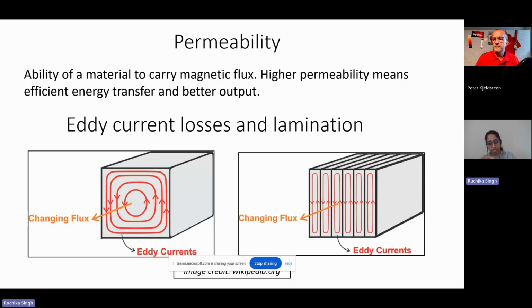coating on the electrical steel, and when you stack them together, press them and heat them up in an oven, the bonding melts, and all the stacks stick together, and there's also a layer of isolation between them. That's how you isolate the laminations, with some coating on it, which creates an insulating barrier between the sheets of the steel.